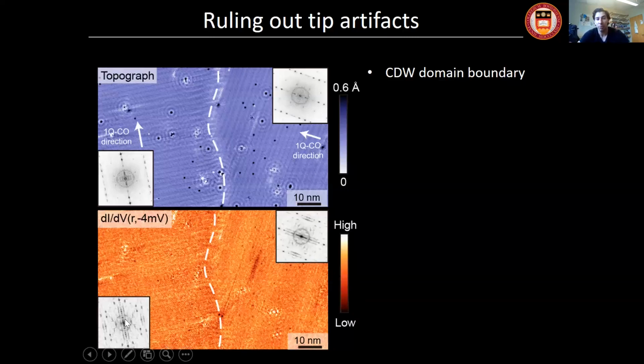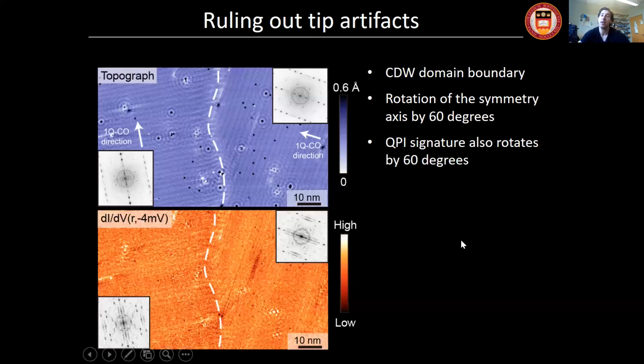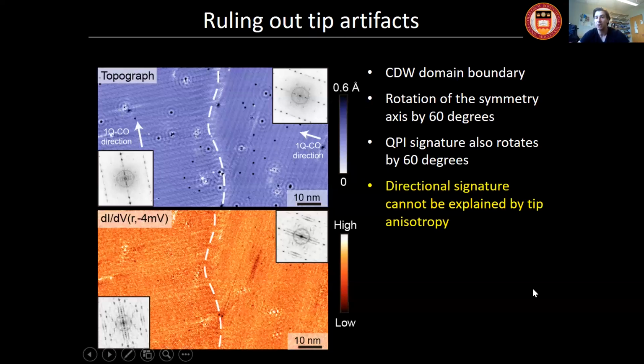And the same with the QPI. So if you look at a QPI, these parallel lines here rotate as well. Okay. So there's a clear rotation of symmetry axis of both the Fourier ordering and the QPI. And this cannot be explained by any sort of tip anisotropy. So what we uncovered here is really a true new charge ordering state that somehow couples to this unidirectional quasi-particle interference signature as well. So it very clearly signals that rotation symmetry at this low temperature in our Kagome superconductor is broken, which is one of the nice signatures of unconventional superconductors as well.